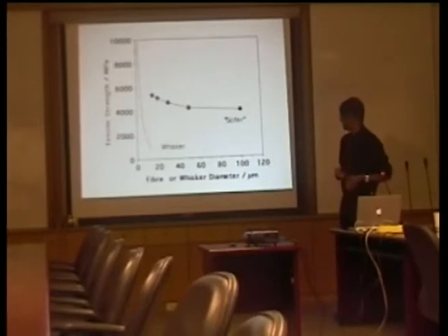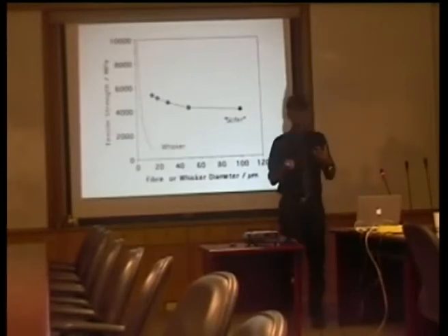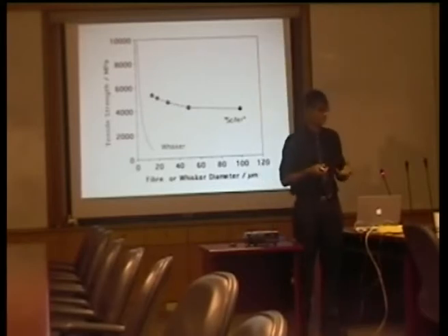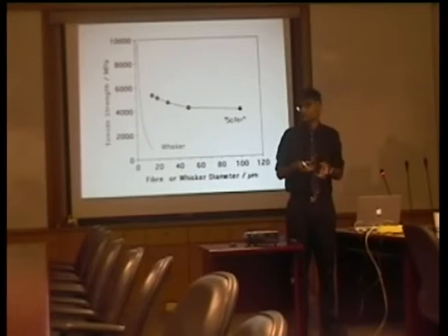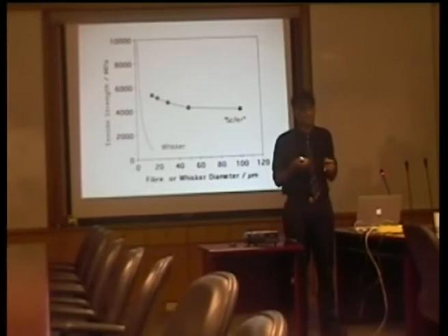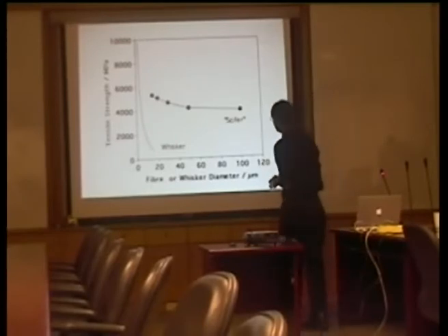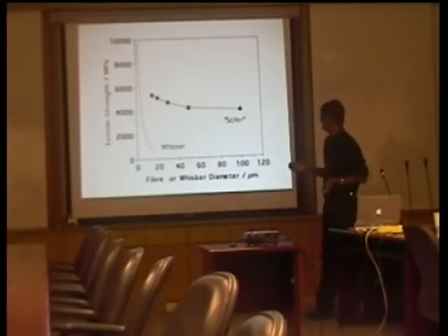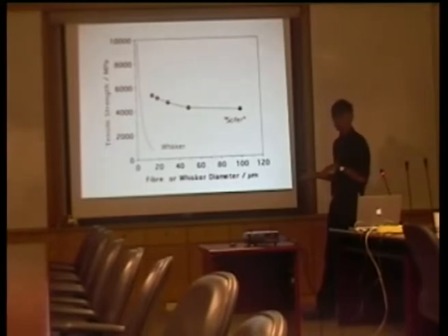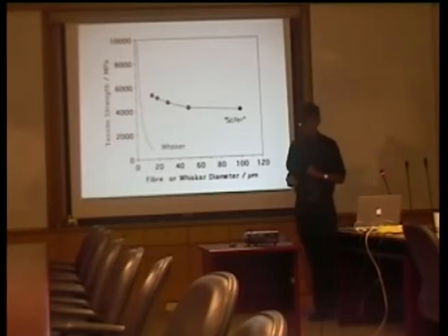So this is not the way in which we might get a strong material. Instead, if we deform the material severely, so instead of getting strength by making the material perfect, we get strength by putting many, many obstacles in the way of deformation, then you can get a material which is strong and insensitive to size. So here, for example, is steel wire which has been severely deformed, and you can see that the strength can be 5.5 gigapascals, and it doesn't decrease as you increase the size of your sample. Whereas this is the original single crystal material. You can see how sensitive this is to size and how insensitive this is to size.